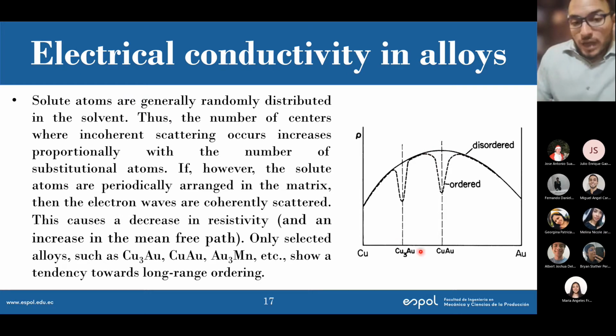Then when I get to that point, an ordered microstructure of, let's say, a 3-to-1 atomic ratio of copper to gold, then I actually have a decrease in resistivity and therefore an increase in conductivity compared to this, right? Not really higher than having pure copper. That will be difficult, but definitely compared to having a disordered arrangement of copper and gold atoms.